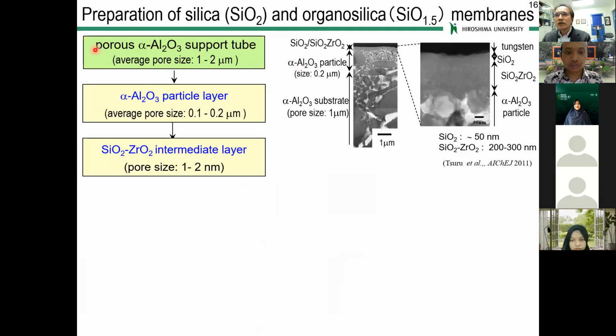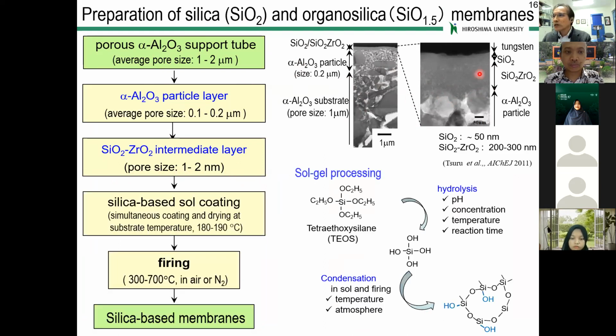Now this slide shows how we prepare silica or organosilica membranes, right? We use the porous alpha alumina support, and then a particle layer is formed, and then we coat the silica-zirconia intermediate layer, which has a pore size of 1 to 2 nanometers. On this intermediate layer, we coat the silica-based sol, and then fire at different temperatures, and then we can get the silica-based membranes. These are the typical procedures.